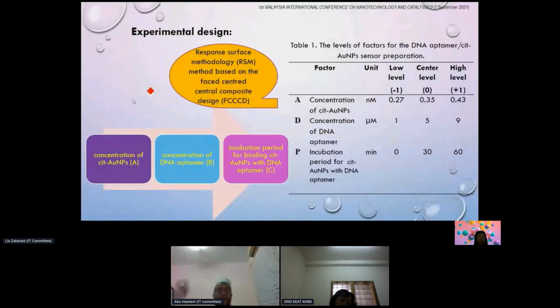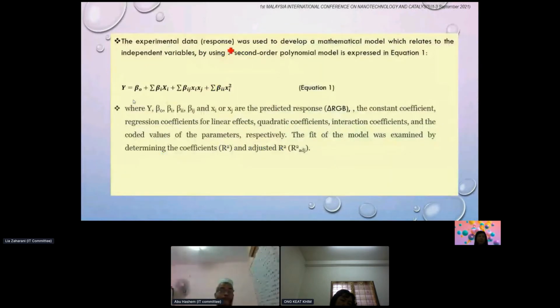This slide shows the experimental design for the detection of MPA. Table 1 shows the three factors investigated at three different levels: low level, center level, and high level. The experimental data response was used to develop a mathematical model which relates to the independent variables by using a second-order polynomial model as shown in Equation 1, where y, beta naught, beta i, beta ii, beta ij, and xi or xj are the predicted response, constant coefficient, regression coefficient for linear effects, quadratic coefficient, interaction coefficient, and coded values of the parameters respectively.